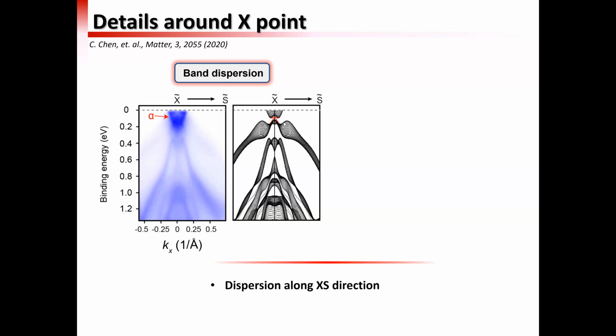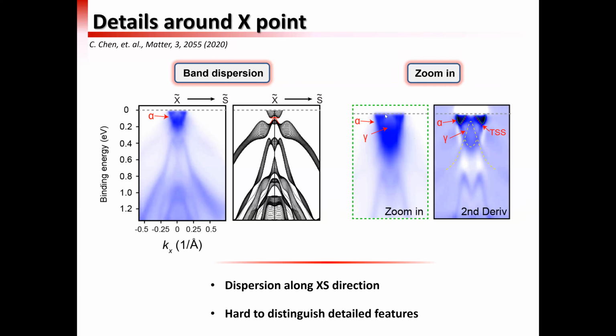But if we want to see the topological surface state here, then we need to zoom in a little bit. The thing is that because the energy scale is too small, the typical synchrotron ARPES measurement doesn't really have the resolution to tell if there is any topological surface state inside this gap between the bulk conduction band and the bulk valence band. Rather, we only saw a bunch of blurry bands. Even if we do the second derivative, we were not very sure whether there's indeed a topological surface state. Of course, it looks similar to the calculation, but we do need to have clearer experimental results.